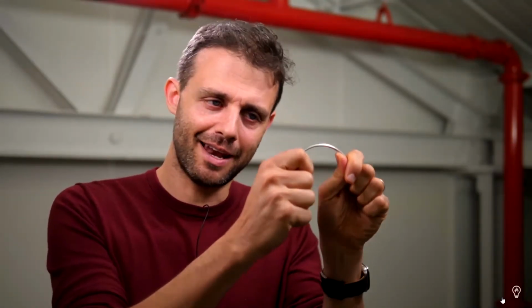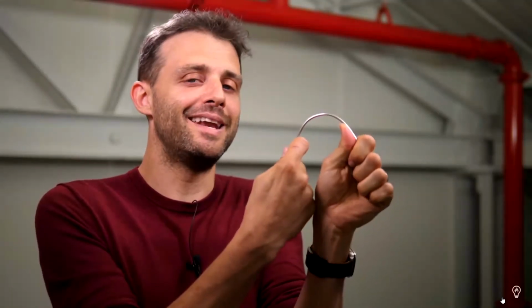You might have thousands of dislocations within a single grain in a metal. So when you're bending it, you're causing those dislocations to glide through the grain. But crucially, when a dislocation gets to the edge of a grain, it can't go any further. It can't hop to the next grain. That's the end of its journey.